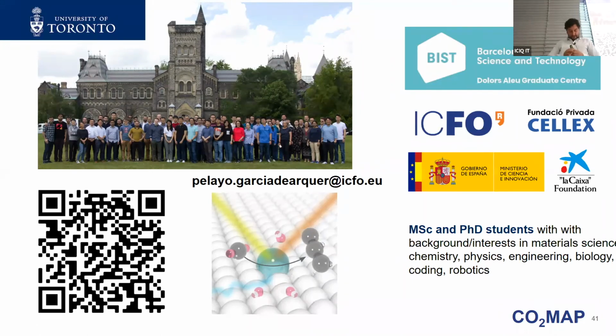Okay, that's a good question, actually. The answer is that it's very difficult to measure the actual local pH of the surface. That's why when we report performance here, we don't measure the pH of the surface. We don't need to know the pH. In these membrane electrode assemblies, you have the full cell potential. You just measure the potential across the anode and the cathode, and that's the energy efficiency that we report. If you were, of course, thinking of potentials versus reversible hydrogen electrode or other kinds of electrodes, that's very important. In the works where the system was performing in alkaline conditions, we were using the high pH, because in that case the bulk pH was similar to the pH that the models estimate for these operating conditions. But you're right, in this more acidic realm, it's challenging, so it's difficult to know the local pH.